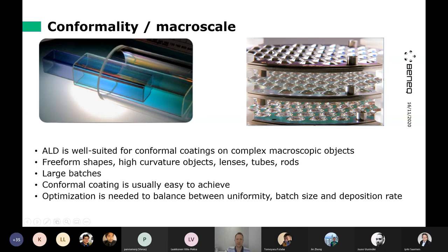It also makes it possible to use a very large batch size. So instead of just coating one lens, we can coat hundreds of lenses at the same time using this good conformality and uniformity feature of ALD. So usually, as a rule of thumb, it's very easy to get conformal coating, so coating everywhere with ALD. It's actually very difficult not to get coating everywhere.